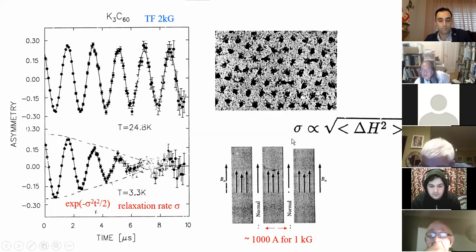But by doing muon experiment, we measure this damping rate sigma, and that is related to the inhomogeneity of this internal magnetic field. And that is also related to something called inverse of the penetration depth lambda. So this penetration depth lambda is the length scale that how the field would change within the superconducting system, you know, how this variation occurs.